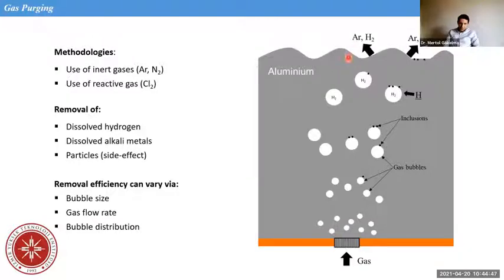So we have bubbles. Usually we have a rotor here, which homogenizes the bubble distribution. And of course, bubbles grow while going up, with the temperature and pressure change, and take the hydrogen from the melt and some particles. Hydrogen goes into the gas, and the particles join the dross. The removal efficiency can vary with bubble size, gas flow rate, and bubble distribution in the melt.